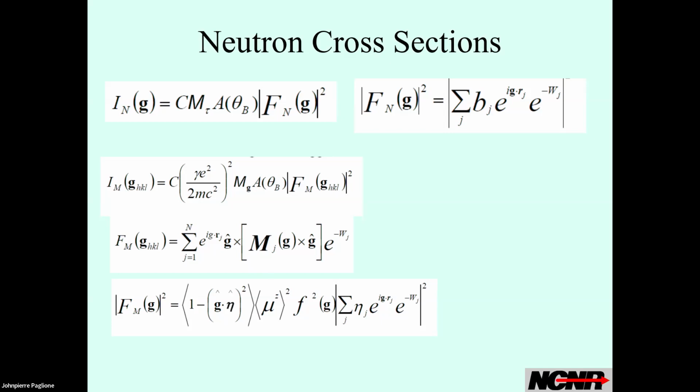Magnetic scattering, I won't go through this, but basically, if you look at the magnetic structure factor squared, there's an orientation factor here that allows you to determine the direction of the magnetic moments. You can quantitatively get out the magnetic moment on each ordered site. That's the expectation value at any particular temperature, pressure, or magnetic field. There's a magnetic form factor because you're looking at the electrons in this case, and I'll show you what that is. And then, of course, you can get the magnetic structure out of them from the usual phase terms.